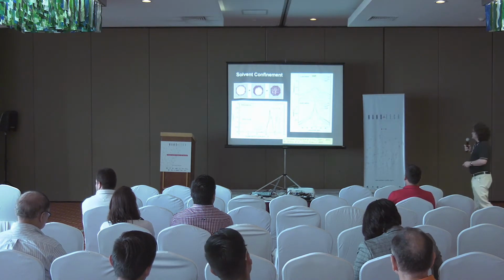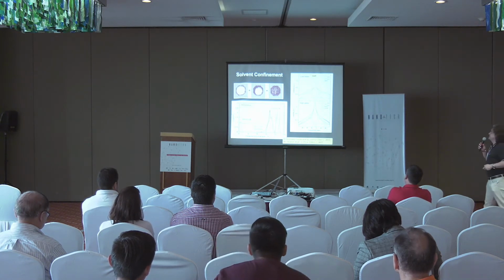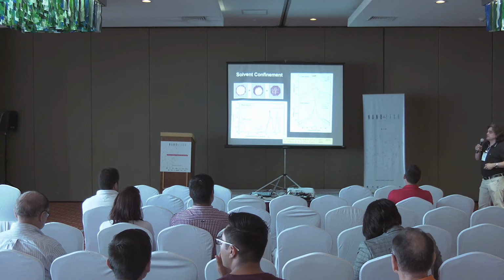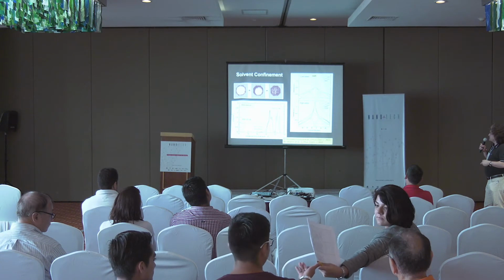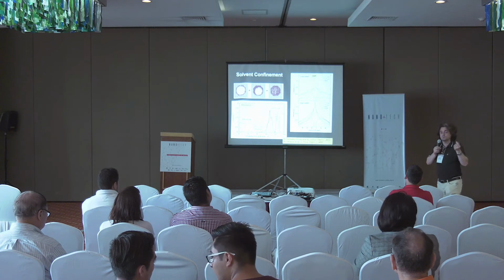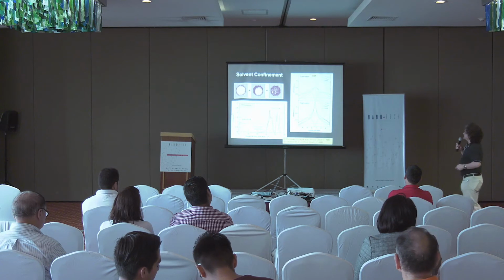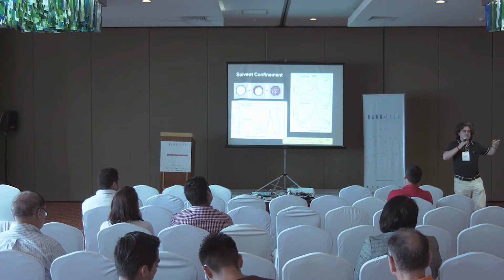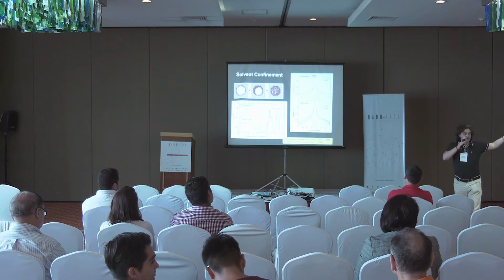Let me show you this. This is a couple of recent works we did, in which we saw solvent confinement here. This is a simulation experiment we did in collaboration with theoretical people, and we made a systematic study of what happened when water, which is a quite complex molecule for absorption processes, absorbs into a 3 nanometer mesopore. 3 nanometers, to give you an idea, is 10 times the diameter of water. So side to side you have 10 water molecules inside a pore.